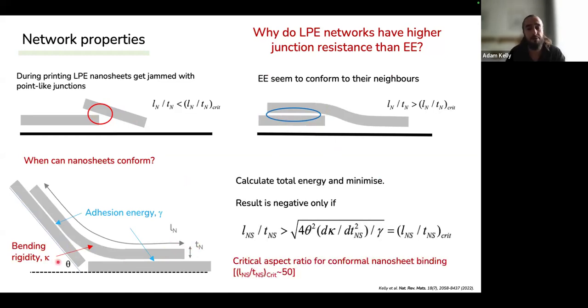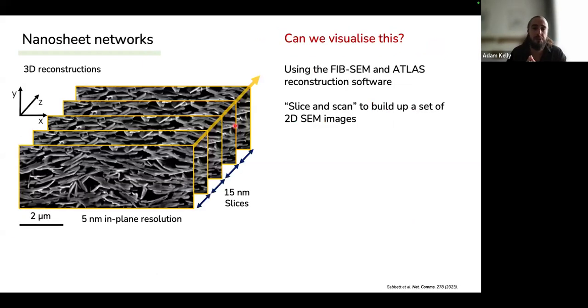And we find if we take the derivative, set it to 0, we calculate the total energy and minimize it. The result is only negative for some critical aspect ratio, some critical length and thickness. And what we find is that number is about 50. And liquid phase exfoliated nanosheets tend to be much lower than that, which means we cannot get bending with these nanosheets. So is there another way to visualize this? Can we actually look at these networks and see what this looks like?